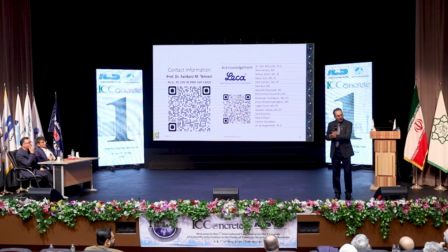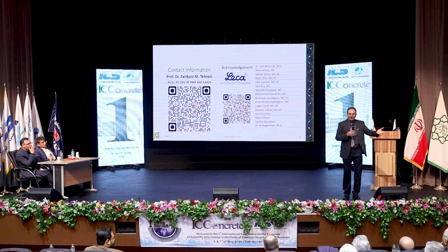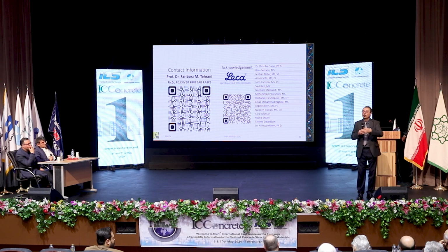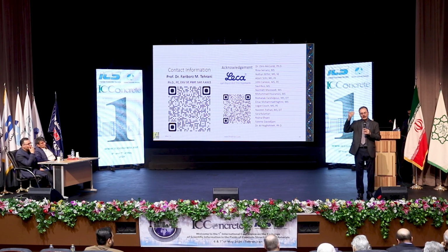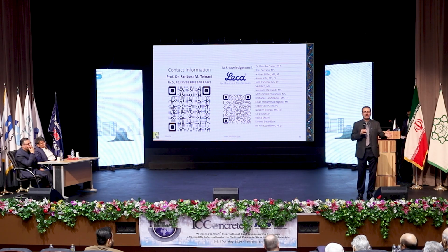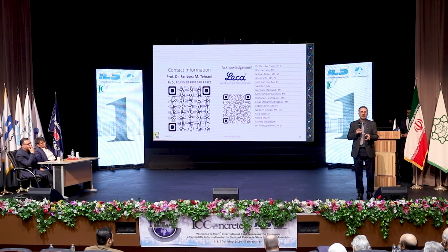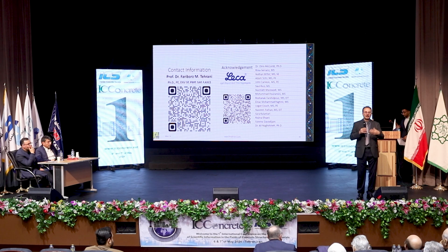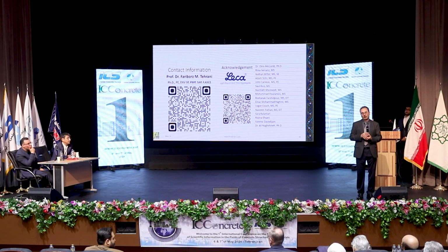There is a difference between different type of concrete. You cannot use the lambda for expanded shale clay slate as the same as slag, or as the same as expanded fly ash, or pumice, or God forbid if anybody uses scoria, please don't, for scoria. So there are differences, and ACI 318 is blind to the source of aggregate, and that has caused a problem. AASHTO has already started claiming that lambda values are not correct, so the new AASHTO is out, they have new data. What we did, we went one step above the AASHTO, and we discriminated between different type of aggregate, and we showed that if there is going to be a lambda value, it cannot be one number for all of them. So that would also help us a lot with people who are dealing with bonding and tensile strength, shear strength that are super important.